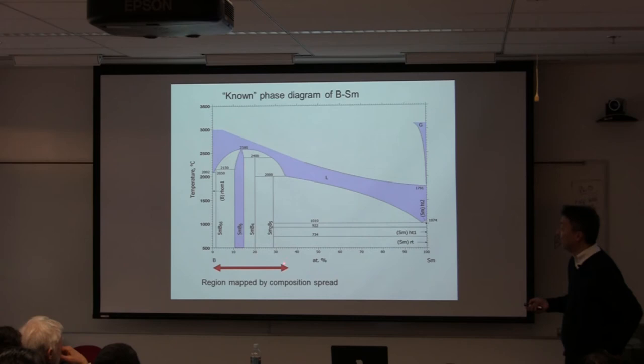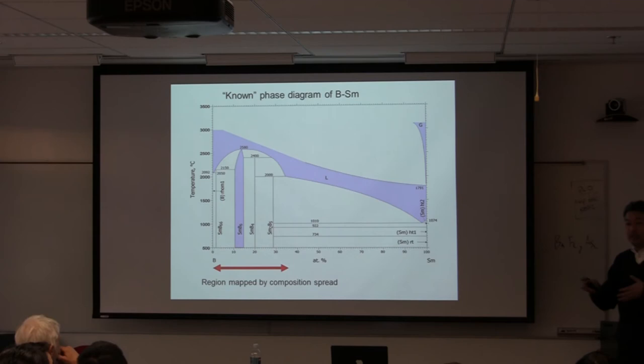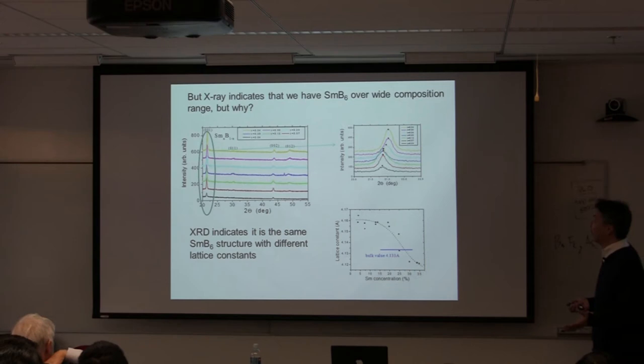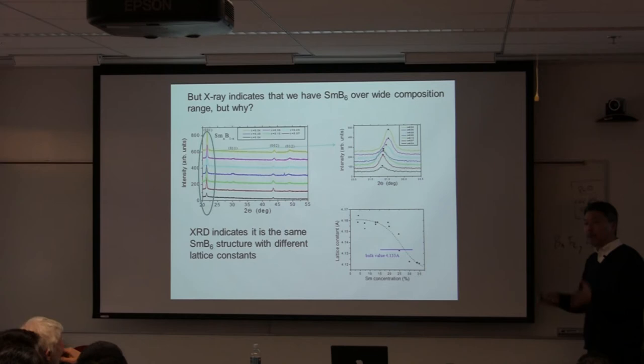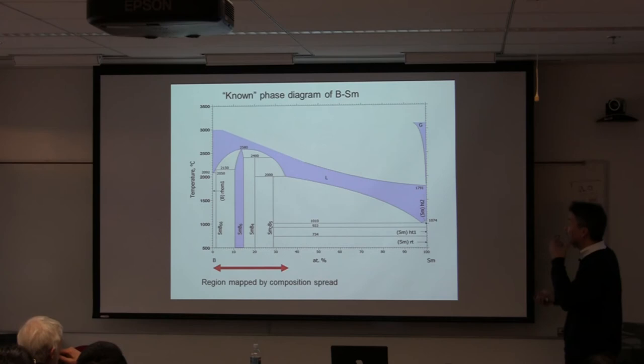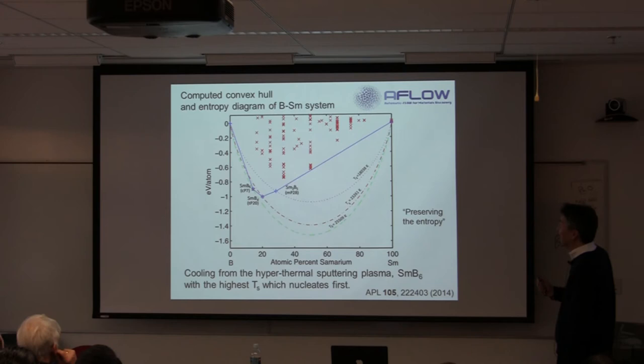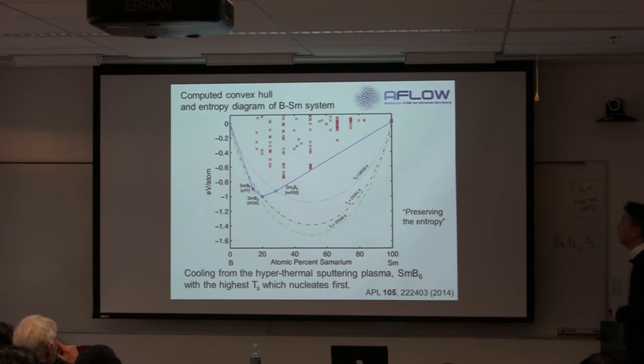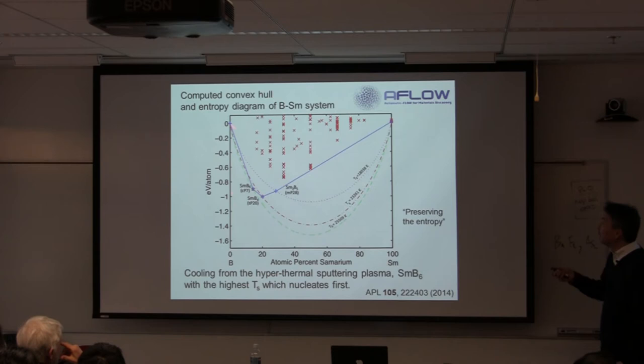Sangin Lee was able to raise the deposition temperature and achieved epitaxial samarium hexaboride films for the first time, enabling angle-dependent device experiments. Similarly, yttrium hexaboride — a known BCS superconductor never previously made as a film — was studied. From bulk studies, reports suggested the superconducting properties vary as a function of stoichiometry. We did a self-composition spread: even when trying to make a uniform single-target film, because the mass difference between boron and yttrium is so large, you lose boron as you move away from directly below the target.